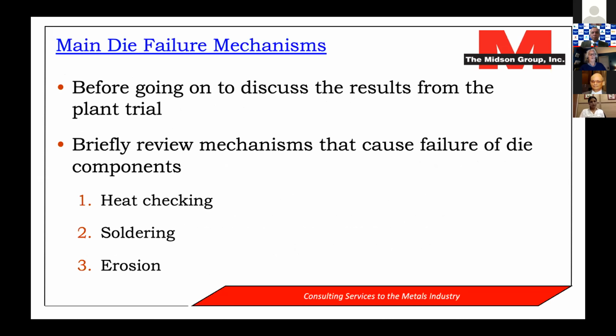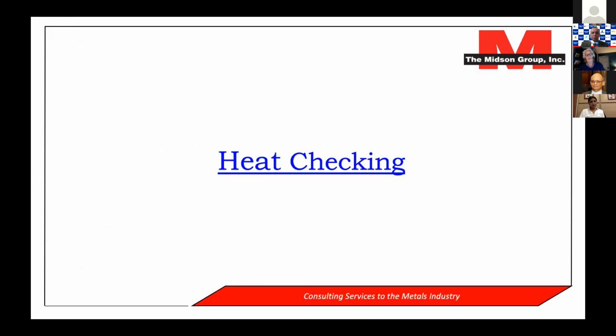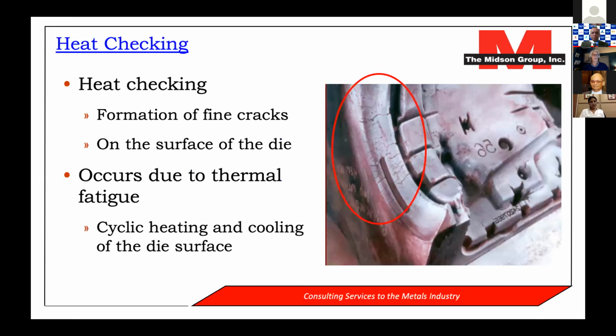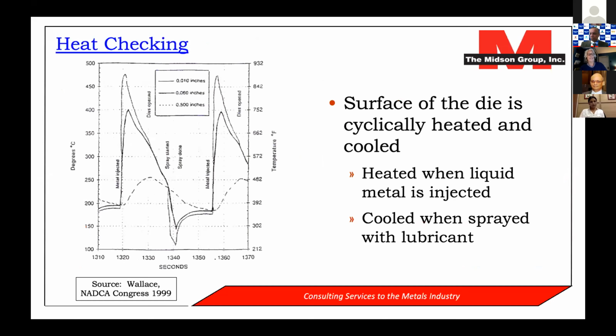Before I go on to talk about the plant trial itself, let me discuss mechanisms that can cause failure of die components: heat checking, soldering, and erosion. Let's talk about heat checking first. As die casters, we're all familiar with heat checking, the formation of fine cracks on the surface of the die. This occurs due to thermal fatigue, which comes from the heating and cooling of the die surface every time we make a casting. This figure is taken from a paper by Jack Wallace and his co-workers from a NADCA Congress paper back in 1999. The vertical axis shows the surface die temperature in degrees centigrade, and on the x-axis we're looking at cycle time in seconds, about 1.5 cycles here.